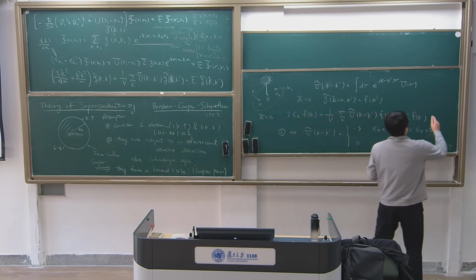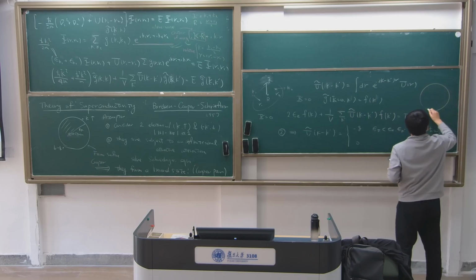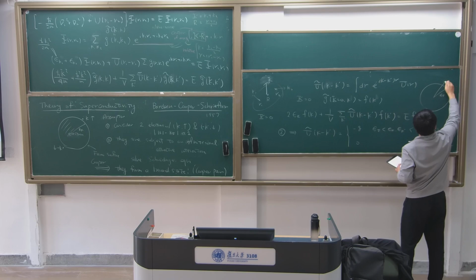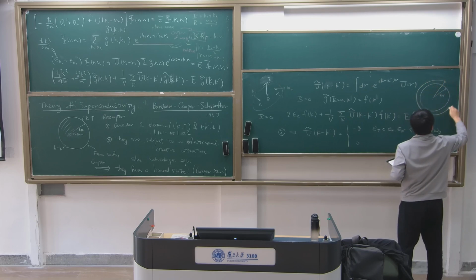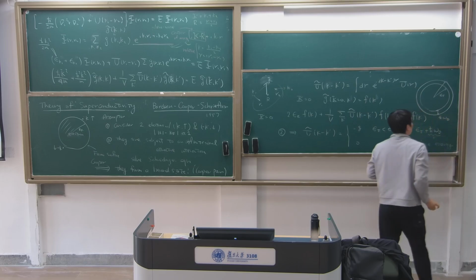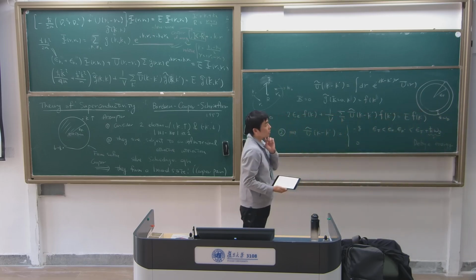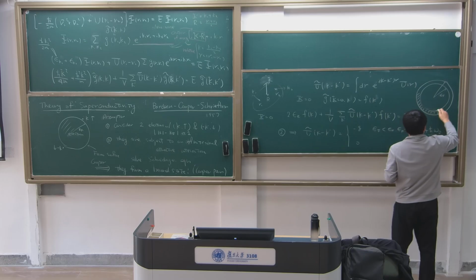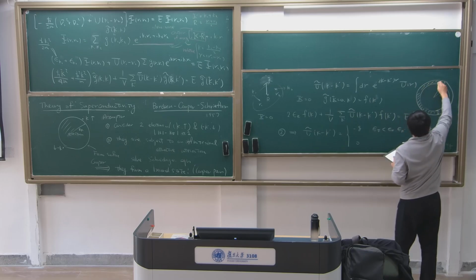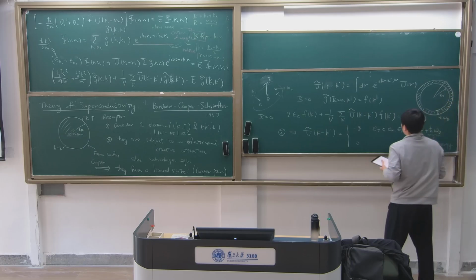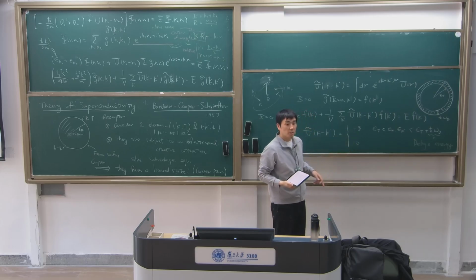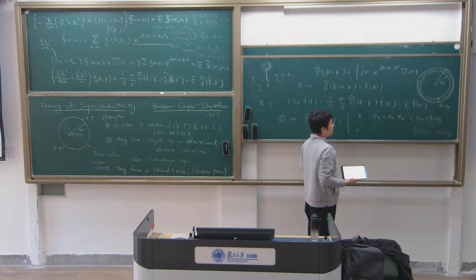So here, you can have a shell, and this length is essentially H bar omega D, the Debye energy. So if the momentum K is inside this shell, then the potential is minus G. Otherwise, you get 0. So that's the second assumption. So Debye energy is the thing.